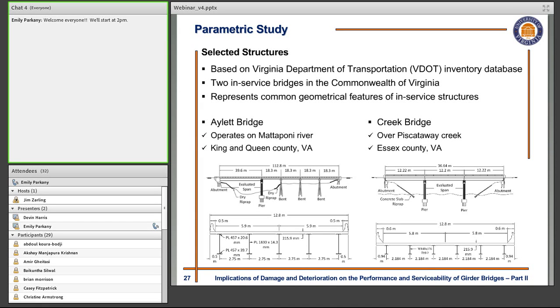The other issue that we had at the time was to have the knowledge regarding the range of damage conditions that may occur in the state. Although we had the inspection reports for both of these structures, these are our representative cases. So we wanted to know how the existing range of damage within the state might affect these representative structures. So at the same time, we prepared this questionnaire or survey and passed it along to the VDOT engineers and inspectors in 9 different districts within the state and asked them to provide the average range of damage that they observe within the state. As we received their responses, we realized that the most common types of damage that they observe in the state are corrosion in the girders and deterioration in the deck.